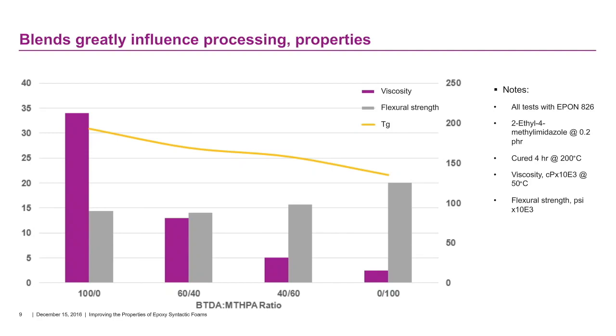And in a syntactic foam formulation, an uncured formulation, clearly you see a viscosity improvement as you add more monoanhydride. I think that's fairly straightforward. But it shows you some of the pitfalls, especially if you would try to make a formulation purely with a solid dianhydride. What would be involved there? From a cured material standpoint, now you start to see some of the trade-offs or the improvements actually.